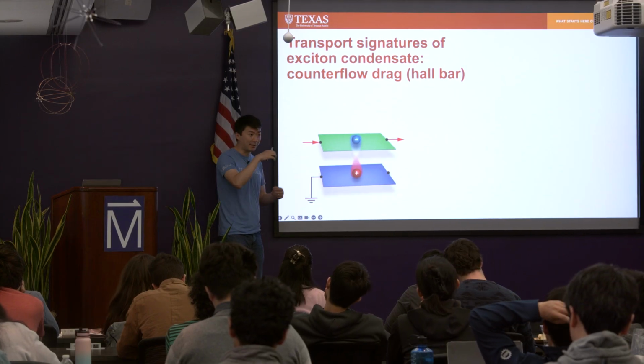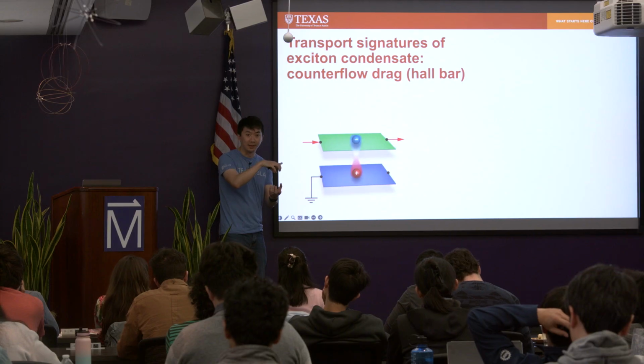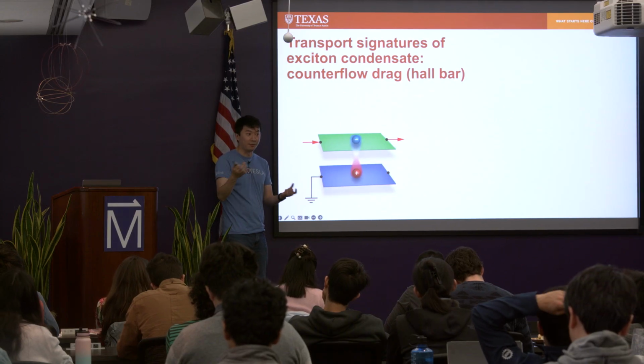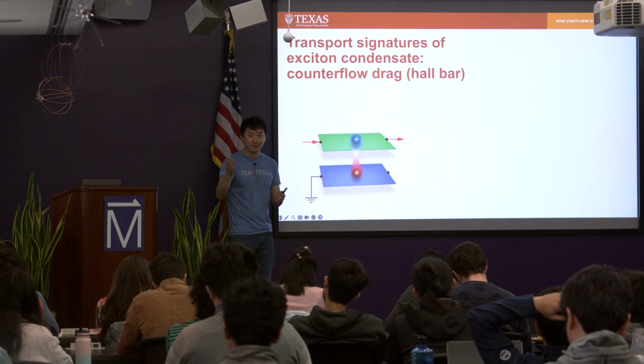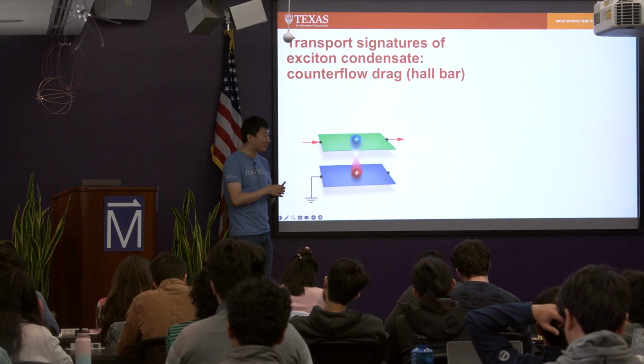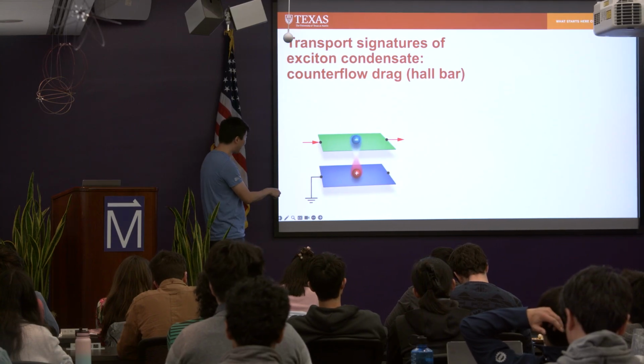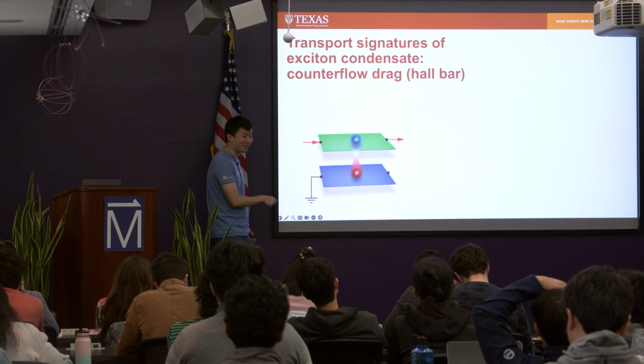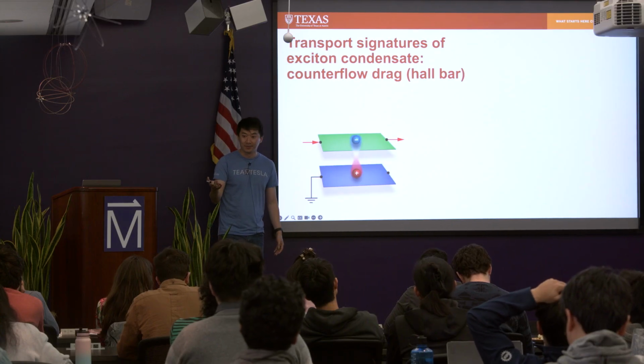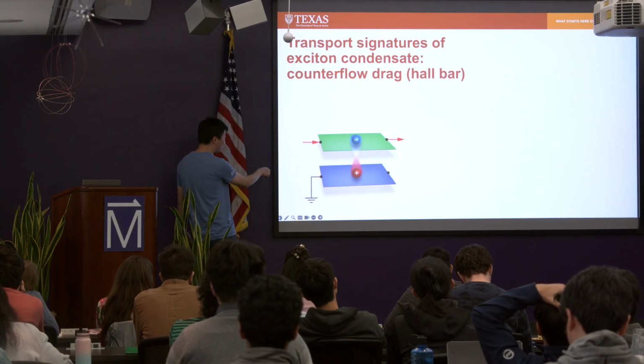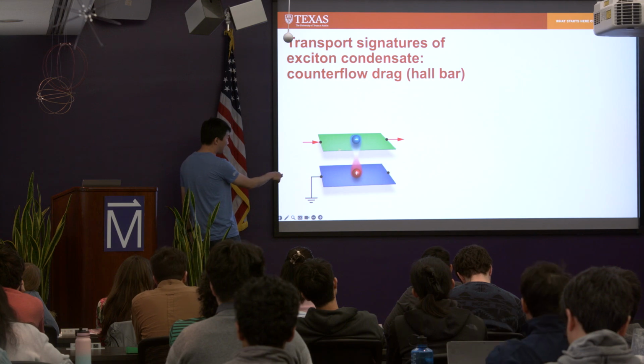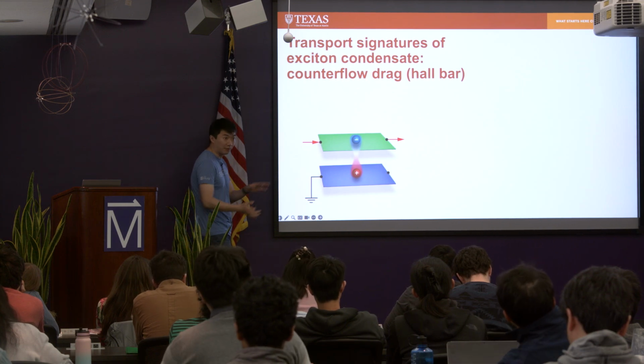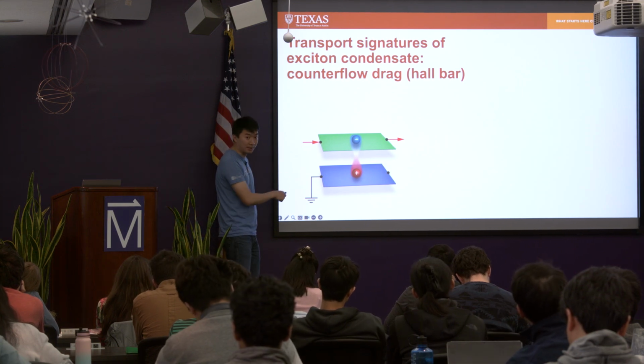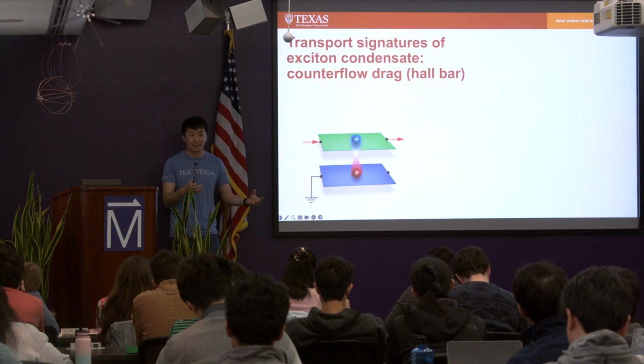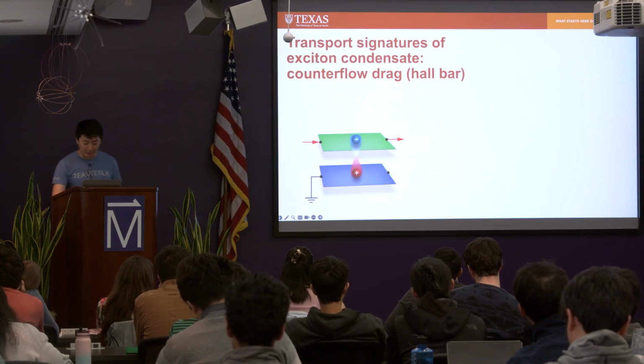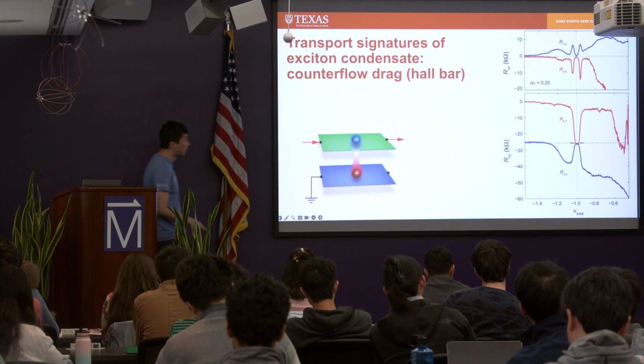When you have exciton condensation, the two layers are coupled together, right? And because you're in the quantum Hall effect regime, there has to be an edge channel. Because the two layers are coupled, this edge channel actually lives on both layers at the same time. Jim Eisenstein called this "which layer uncertainty," right? So when you inject current on the top layer, there's an edge mode that flows on both layers at the same time, even though the bottom layer is completely electrically passive, right? And then that shows up as this measurement.